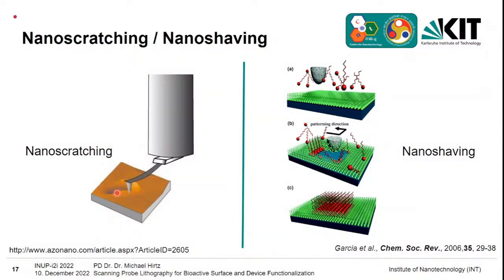This then allows you to modify the surface by scratching. When you do it on monolayers, like self-assembled monolayers of molecules on the surface, to remove single molecules, it's also sometimes called nano shaving, because you're really only taking away the first layer of molecules. This allows you, for example, to backfill with other molecules, to create different chemical contrasts on surfaces.